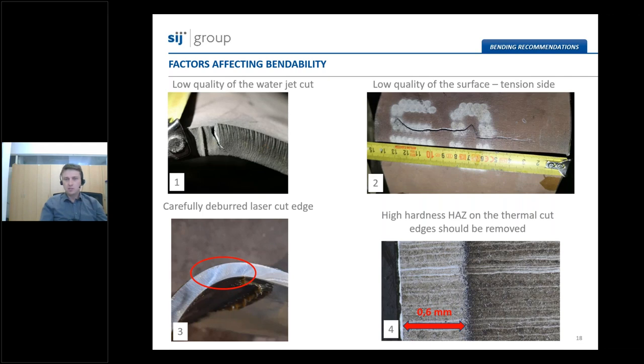So if possible, we recommend to remove the heat affected zone region when bending steels with really high hardness. One example could be SIDUR 450 or SIDUR 500 grade. And if possible, you should remove the heat affected zone at least on the area of the bend radius.